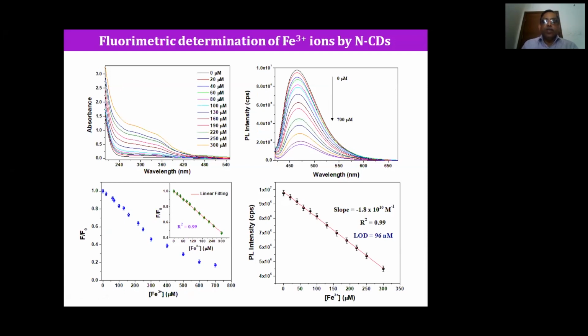When you look at Fe3+, it was sensing for the Fe3+ ion. As you increase the concentration of Fe3+, the fluorescence intensity decreases, so it's again a quenching mechanism of sensing the metal ion. We could find the LOD of around 96 micromolar for this material.